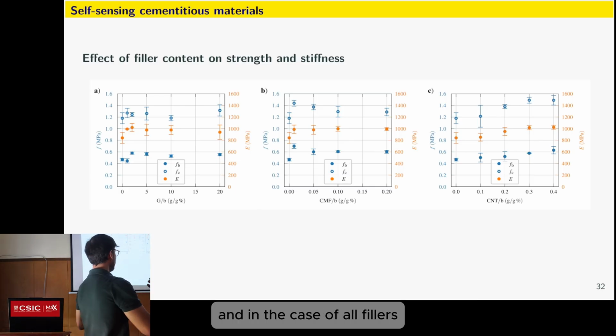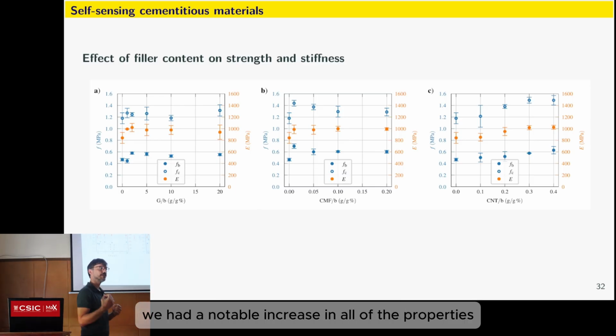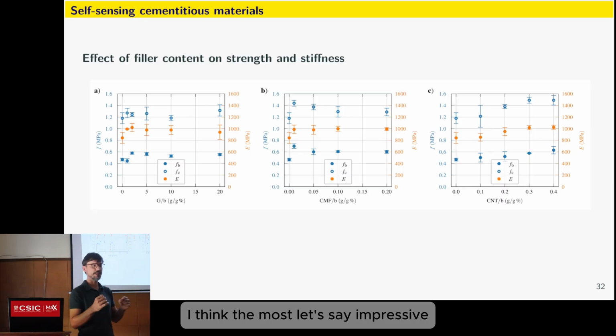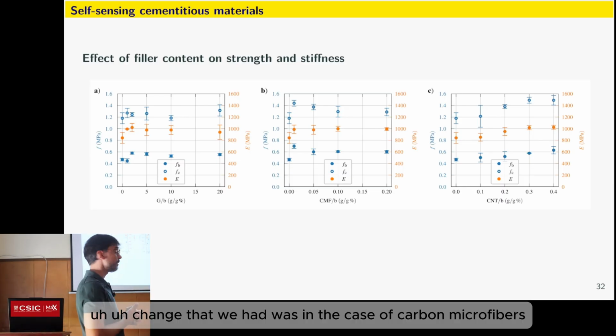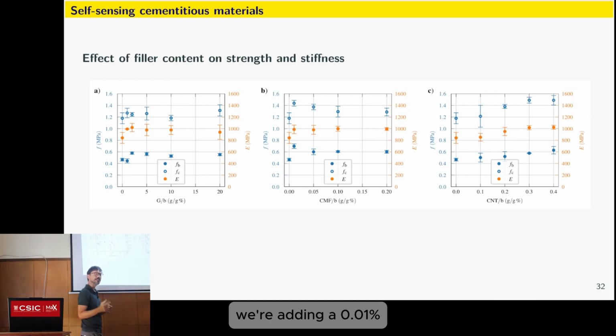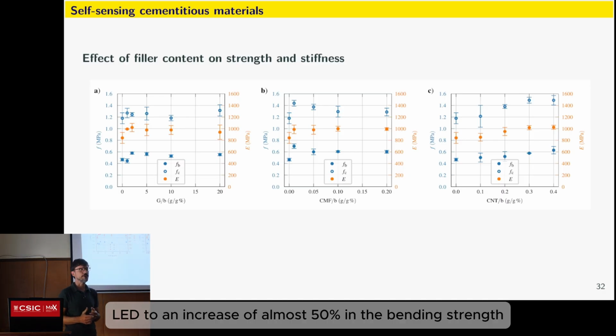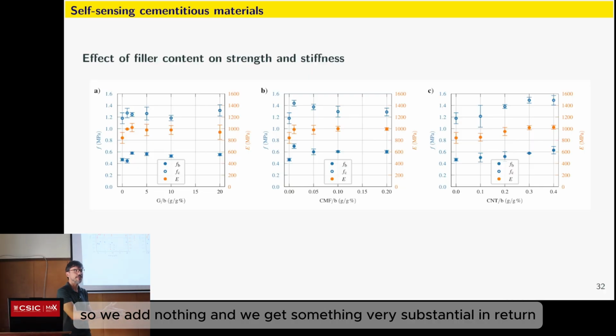And in the case of all fillers, we had a notable increase in all of the properties. I think the most, let's say, impressive change that we had was in the case of carbon microfibers. Adding 0.01% led to an increase of almost 50% in the bending strength. So we add nothing and we get something very substantial in return.